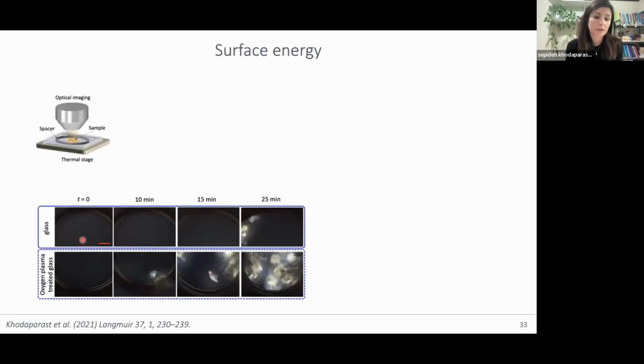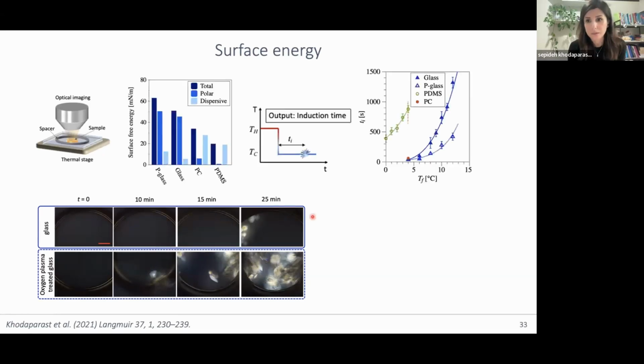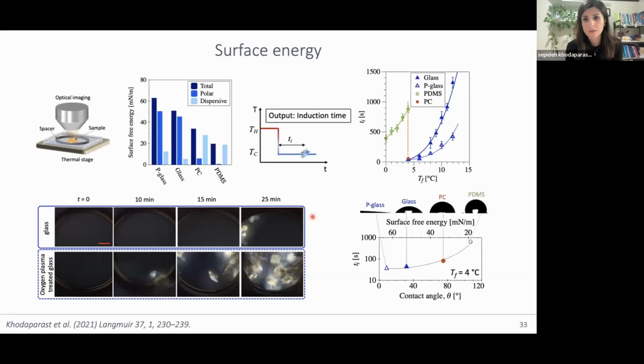So I'm looking at the image of the droplet under a microscope. In the first scenario, the surface is glass. In the second scenario, the surface has higher energy because we just plasma treated the glass, and you see that in time, from left to right, from early times to later times, when I plasma treat the glass, crystals start appearing much faster. I'm just going to go through these a bit faster.